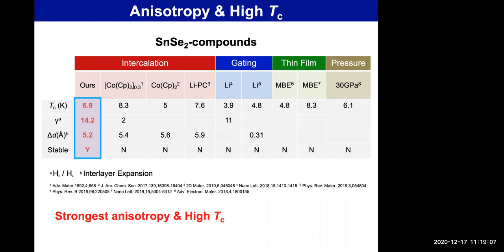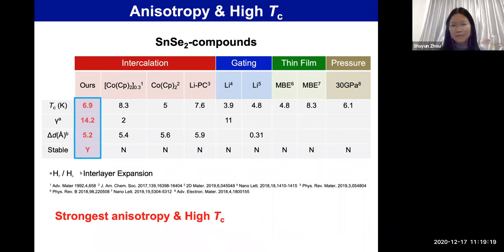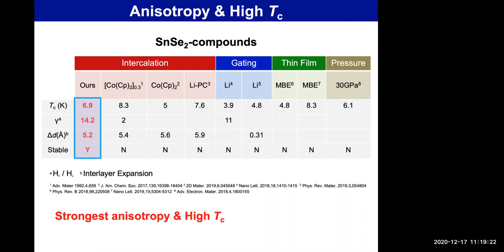So there is a dome in TC as a function of interlayer spacing. TC goes up as you insert more and more layers, and at some point, it starts to go down again. This has puzzled the community a lot. So then the idea was that anisotropy is very important: the more isotropic the compound, the lower the TC. And this brought back the discussion of spin fluctuation theory in heavy fermion compounds that are even older.